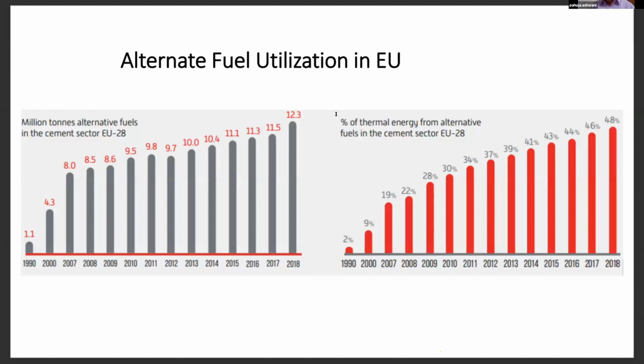Now, this utilization of alternate fuels in the cement sector started mainly in the early 90s, with only 2% alternate fuel thermal substitution in 1990 in the entire European Union. Today it has moved to around 48% in 2018, and currently it is close to 50-52% thermal substitution rate in the European Union. As against this, the Indian cement sector today is only at 4%. Well, there are reasons, as I mentioned earlier, that there have been not very favorable policy drives, but in the last few years, it has started picking up.